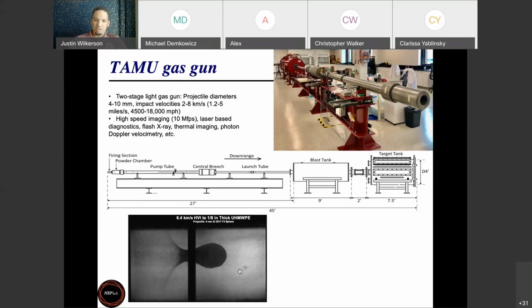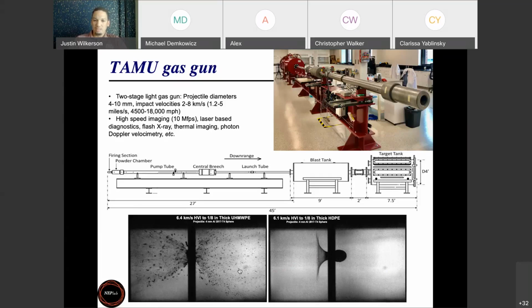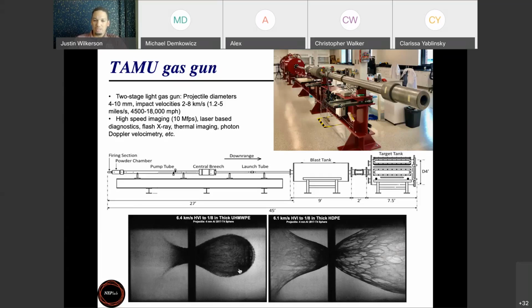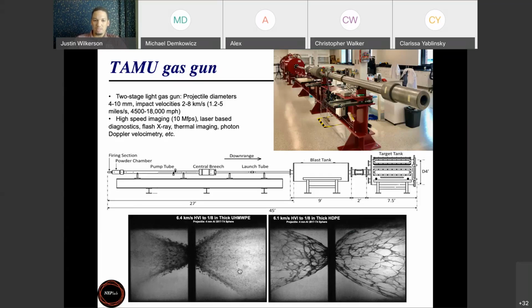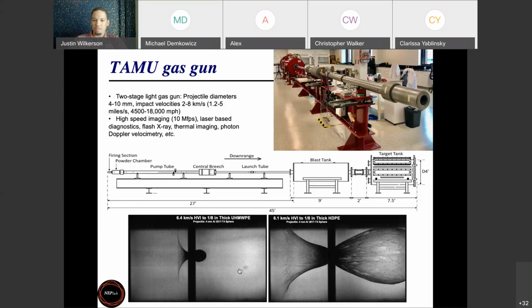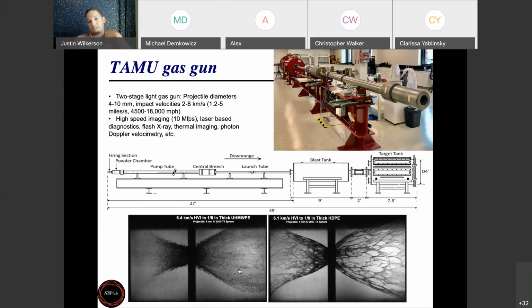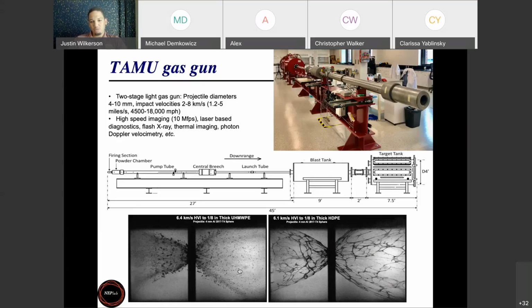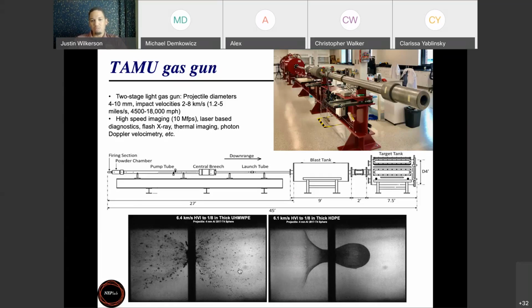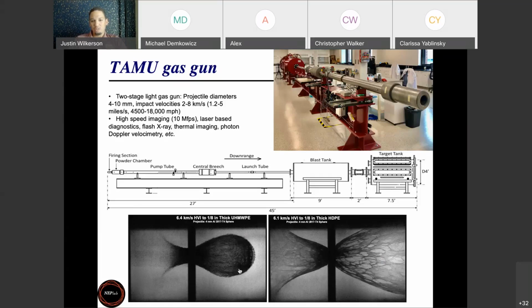Next, I'm going to show a video of a fairly similar polymer from a molecular standpoint, but it's going to have an extremely different failure mode in this hypervelocity impact situation. This is high density polyethylene impacted at very similar conditions, similar thickness, same projectile. Everything's pretty much the same, but you can see that we have a totally different failure mode. Here it looks more like a membrane-like failure, a soap bubble type failure. It looks a lot more ductile. You see a lot more stretching and deformation.